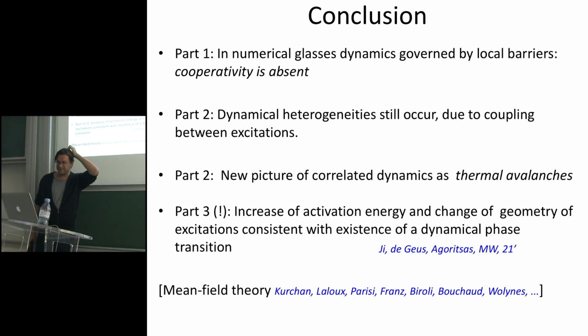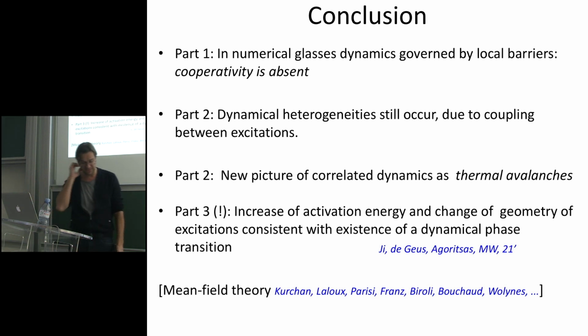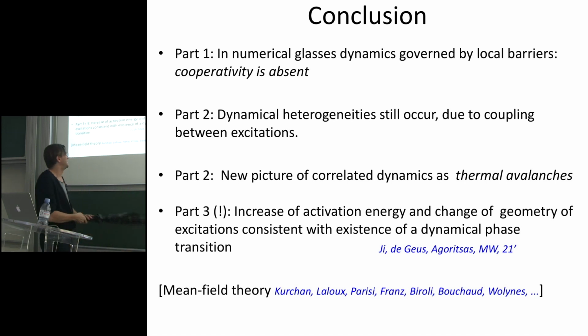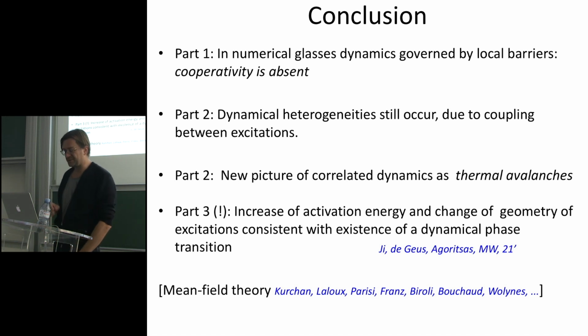Part three that I wanted to tell you about is the question of, yes, but why is it that those barriers grow in energy as you cool the system? And for elastic models, it's just because the shear modulus increases. We think there is much more physics behind that, because we see that not only the energy of the excitation changes, but also their geometry. Okay, this is essentially discussed in this paper. So if someone is interested, you can look at that. And it also makes a direct connection with mean field views on the glass transition. But I could take questions on that, though I don't think it's worth entering into it now.